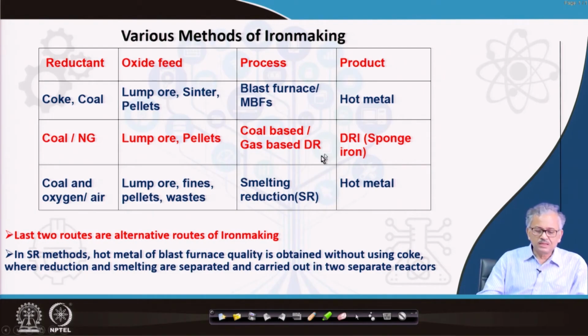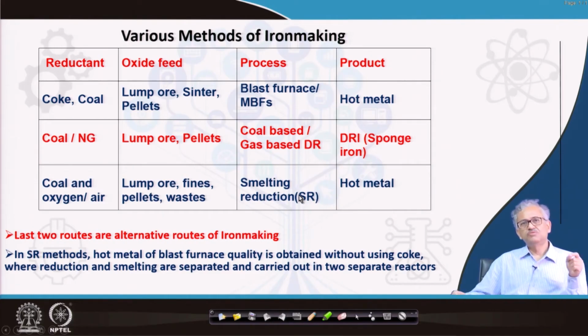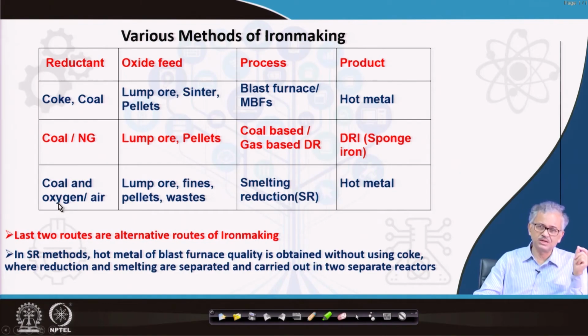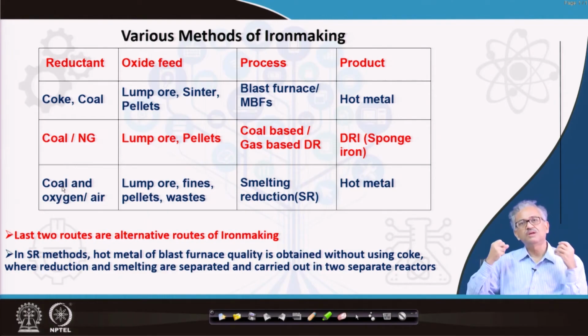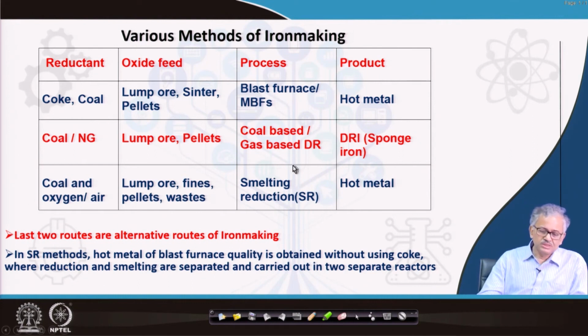And then another process is the smelting reduction process. Here what you do is first melt the iron ore itself by generating intense heat by burning coal in the presence of oxygen. In most cases pure oxygen at room temperature is used, and it burns with the coal forming intense heat, and in that heat you can melt everything. So you melt the iron ore also, and then in the liquid state you can reduce it. That was the definition of the smelting reduction process, but nowadays you do it in a two-stage process also. I'll come to that. So in a single stage, you melt everything. That is the idea of smelting reduction.